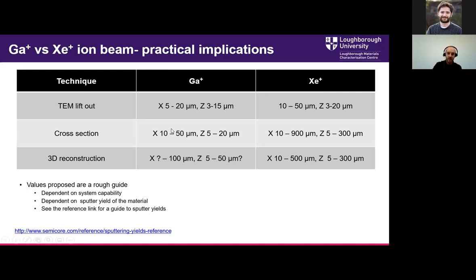For cross sections, again, sometimes for very small cross sections, gallium might be more efficient. And if you want to do ion beam imaging, gallium is still much better than xenon, as you get much more contrast and much more channeling in gallium than you do with xenon.